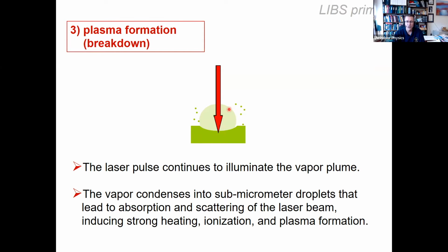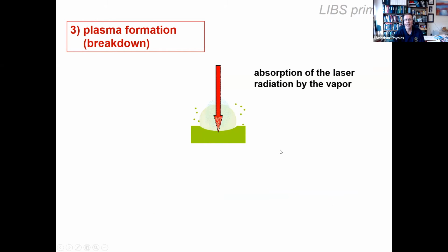And that's just going to create very strong local heating of that gas cloud, because eventually what happens is the cloud gets so dense with stuff you boiled off, the laser can no longer reach the surface. We call that laser plasma screening, plasma shielding, and you stop removing mass. And now all that laser light, the energy must go somewhere. Where does it go? It goes into that cloud.